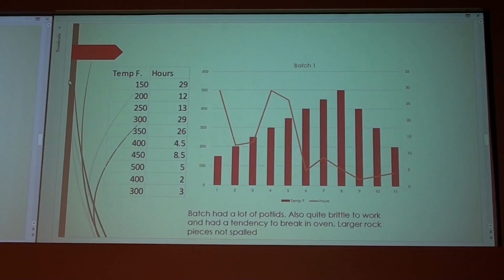And what I did is I went through different temperatures and different hours of actually heating it. So the vertical bars are the temperature, and the line is how long I held it at that temperature. And so this batch, I purposely heated it a lot, slowly at the beginning, to make sure that all the water was driven off. You can see it was 29 hours at 150 and then 12. And then 250 would have been the first time you had to worry about heating. And I still wanted to heat it slowly.